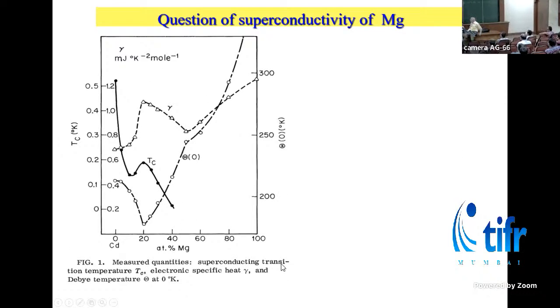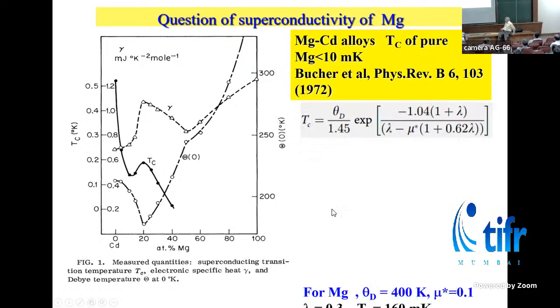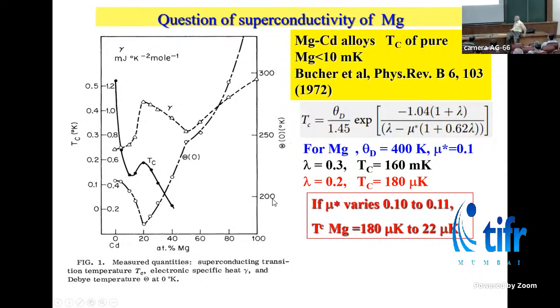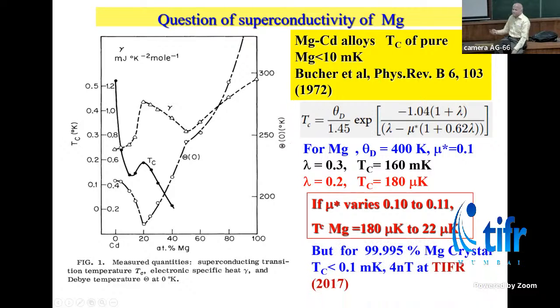Okay, so let me come to this magnesium problem. So magnesium was a hole in the periodic table again. And so what do we do? How do we predict something is going to superconduct or not? So we take a known superconductor, make an alloy. If you form a solid solution, you are lucky. If there are going to be crystal structures well defined, you are not lucky. You are stuck. But magnesium, people tried this. And they said that, experimentally, it has to be below 10 milli-K.